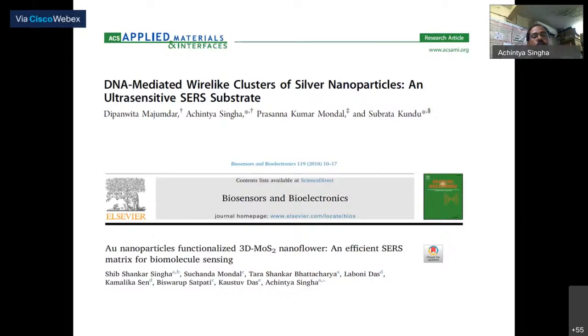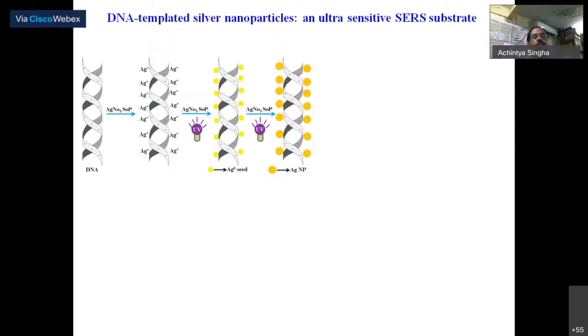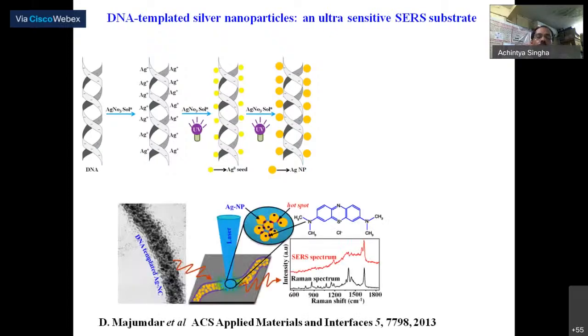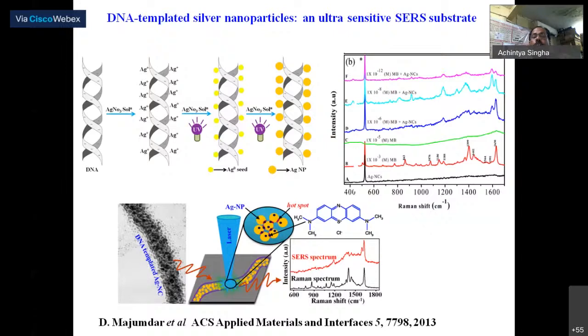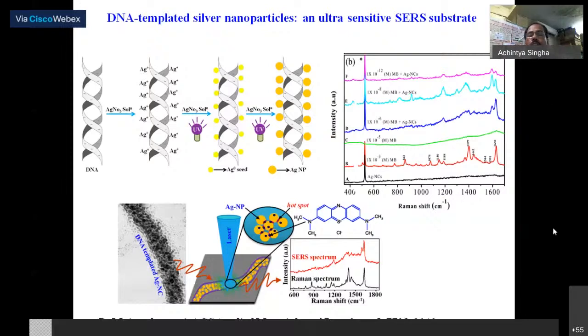So in the first work, yeah, we use DNA and we grow the nanoparticle on the surface of the DNA, and that DNA mediated nanoparticle acts as the substrate for SERS, and we adsorb the methylene blue molecule for Raman measurement. Next, yeah, you can see we can measure the Raman intensity of this methylene blue molecule up to the picomolar concentration.